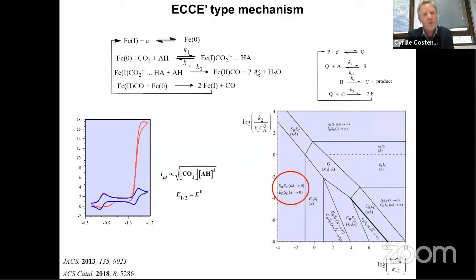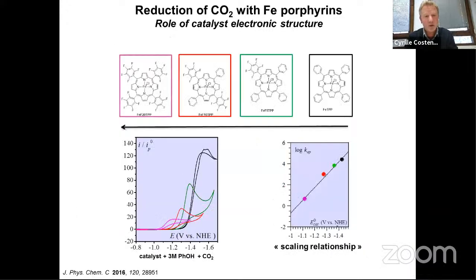a reaction order of 1 in acid as you increase the concentration of acid is because at high concentration of acid, you pull on this so fast that this process here becomes irreversible. And actually what you do is that you move this way in the zone diagram and you make this initial pre-equilibrium process irreversible. Okay, so this is what we can get from the experimental observation.